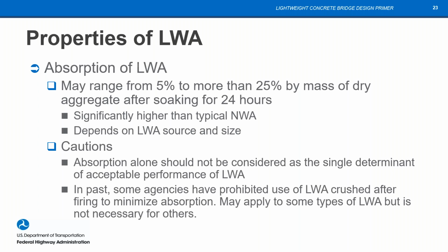And one thing that we should call a caution here is that absorption alone shouldn't be the only criteria considered to determine acceptable performance for lightweight aggregate. We need to look at the whole picture there. And in the past, some agencies may have also prohibited the use of lightweight aggregate that's been crushed. California used to have that in a spec, and that was to minimize absorption, but that was for the type of aggregate they had out there. If we're looking at it nationally, that's not a necessary requirement, and may not even work for that one. But at any rate, it's not something we want to do. So those are some cautionary statements there.